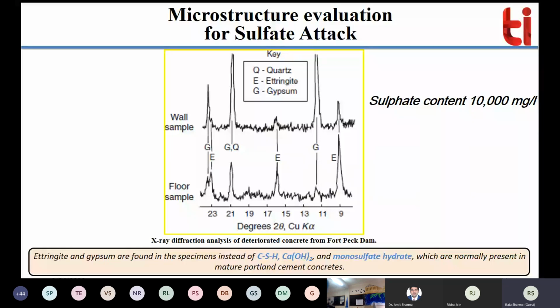That significantly shows that sulfate is very high in that water, and it is directly in contact with the concrete floor and wall. They found peaks at 2 theta, where E or G shows ettringite and gypsum, and Q is quartz, which is very little, but ettringite and gypsum are showing the peaks. In normal concrete, when you do the X-ray diffraction analysis, you will see the peaks of calcium silicate hydrate, calcium hydroxide, and other compounds, right?